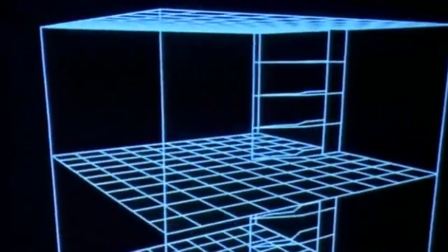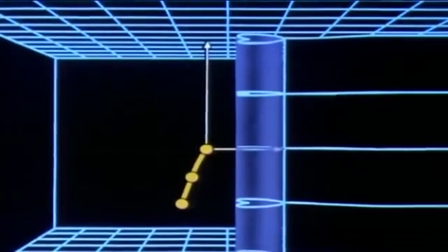The situation changes if we introduce the effect of plasticity at the crack tip. Near the centre of the specimen, we can still identify points that are relatively far from the free surface compared to the distance from the crack tip, where a state of plane strain exists. If the plastic zone lies within this region of plane strain, any fracture will still feel the constraints of plane strain.